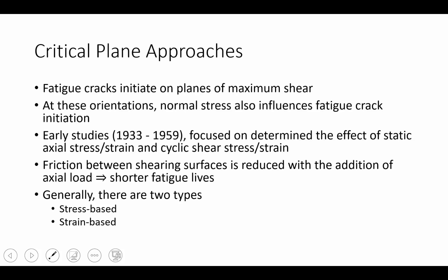How do we manage this relationship between normal and shear stresses? One approach is to introduce the critical plane approach. In the critical plane approach, fatigue cracks initiate on planes of maximum shear, and at these orientations, normal stresses also influence fatigue crack initiation. Early studies focused on determining the effect of static axial stress or strain and cyclic shear stress or strain, where friction between shearing surfaces is reduced with the addition of axial load, resulting in a shorter fatigue life. Generally there are two types: stress-based and strain-based, though the most successful is a mixed approach that includes strain energy.